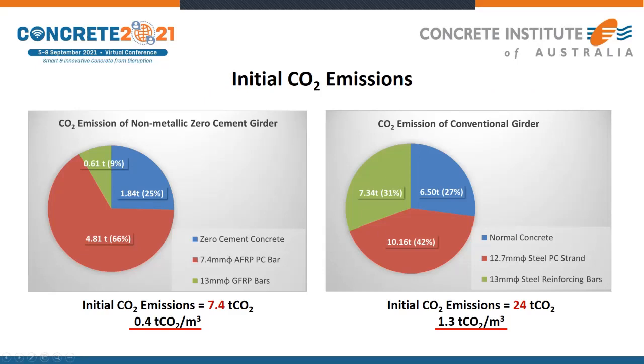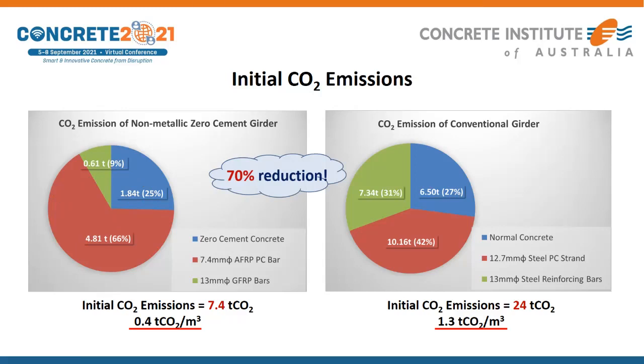And this is the result in initial CO2 emissions. In the conventional concrete girder, the total CO2 emission is about 24 tons CO2. On the other hand, the zero cement concrete is 7.4. So as you can see, the concrete reduced from 6.5 to 1.84, tendons 10.16 to 4.8, and reinforcement 7.3 to 0.6. So in non-metallic zero cement concrete, the CO2 emission from the AFRP is dominant, but totally we can reduce the CO2 up to 70% as a structure of the girder.